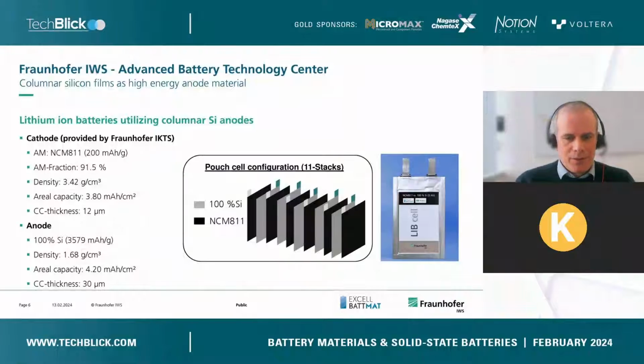So based on this experience, we built multi-layer pouch cells and used 100% silicon anodes, double-side coated, together with NCM 811 high energy cathodes provided by our partners from Fraunhofer IKTS. And these multi-layer pouch cells have been built and tested with reasonable areal capacity. So it's aiming to demonstrate relatively high energy density.